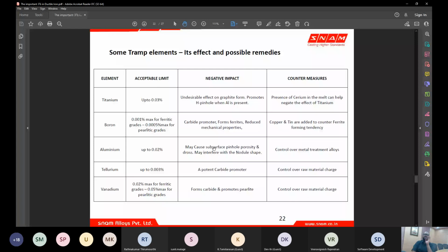Also, it is dangerous when added in excess. When aluminium goes beyond a limit, it can lead to more dross formation, because when aluminium becomes alumina, Al2O3, this alumina can react with other oxide forming elements available in the liquid metal, and it can lead to coagulative dross or coagulative oxide defects.